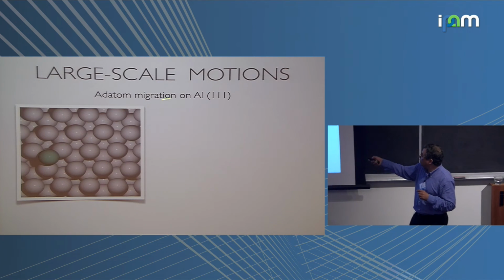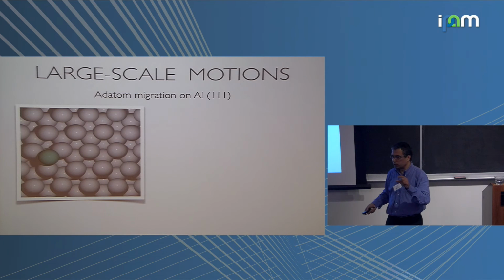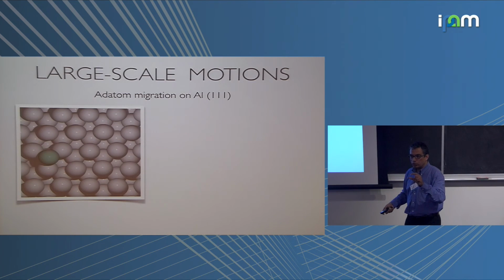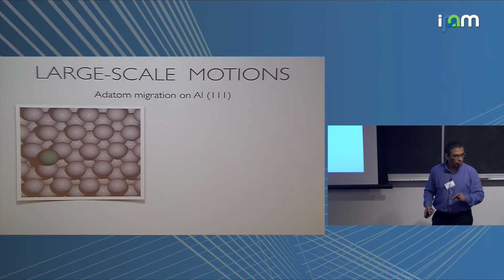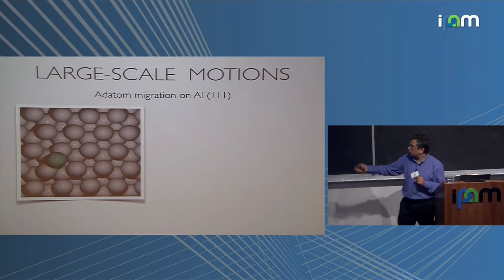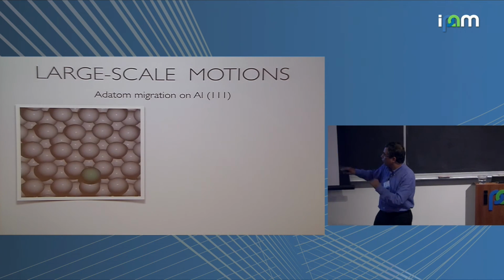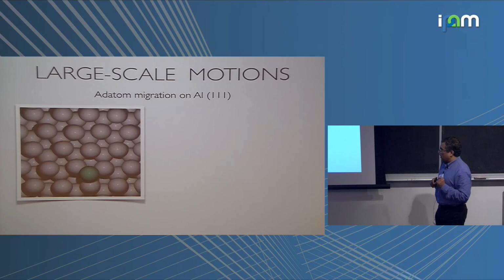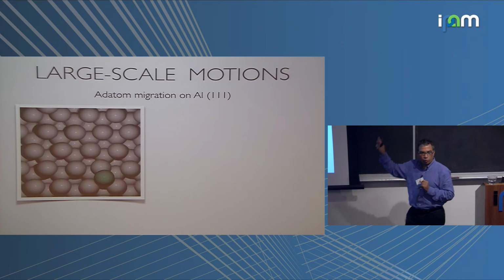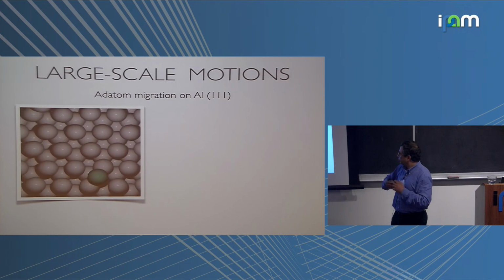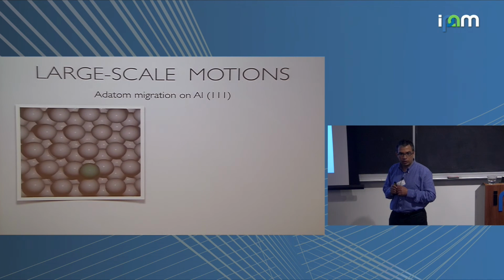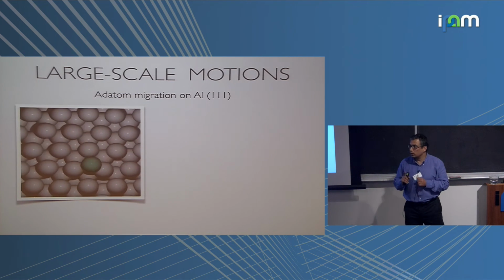Here is another example, of diffusion. Here is an aluminum 111 surface, and there is an aluminum adatom on the surface. We wanted to model the long-range diffusion of that adatom. That's the simulation over here using this force field. The atoms are jiggling around, the adatom is moving around, spanning a huge time scale in the simulation. But the real question is, yes?